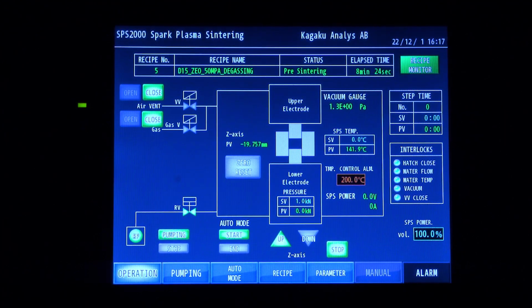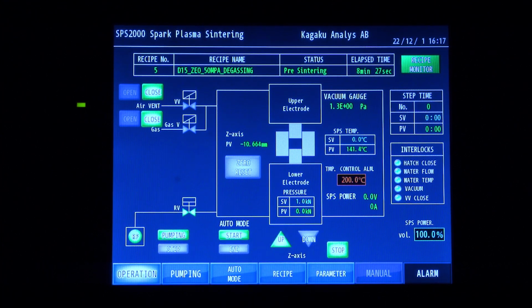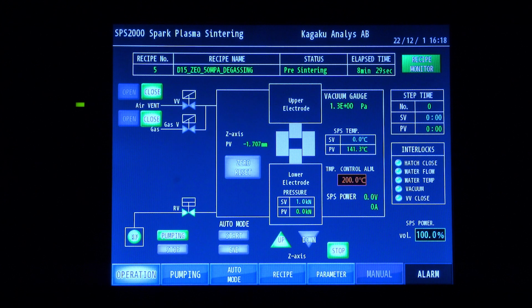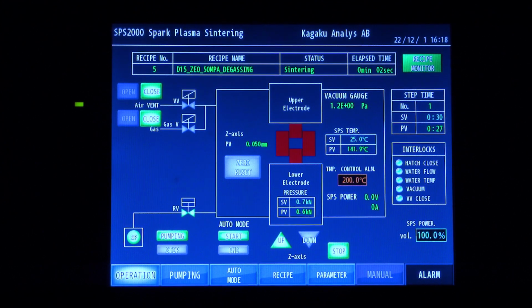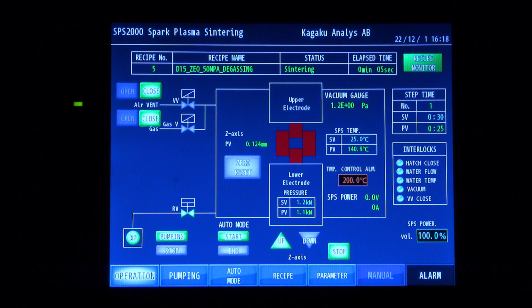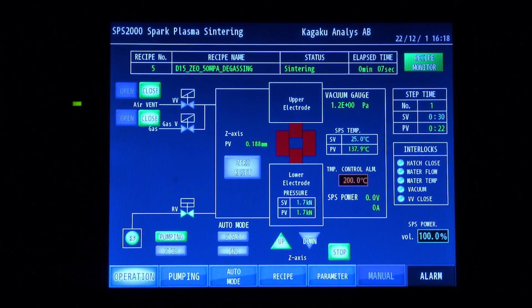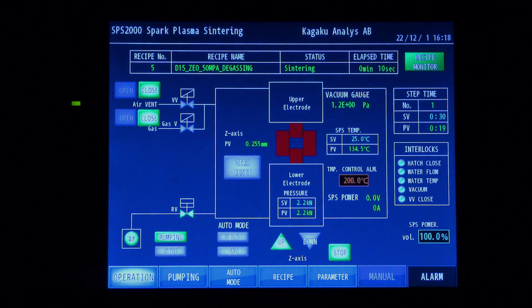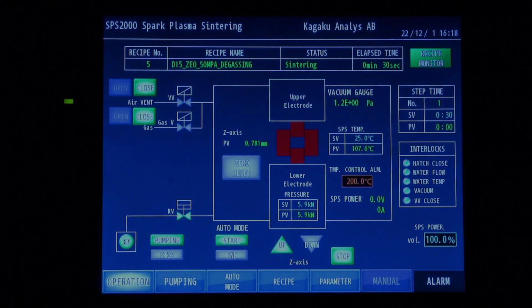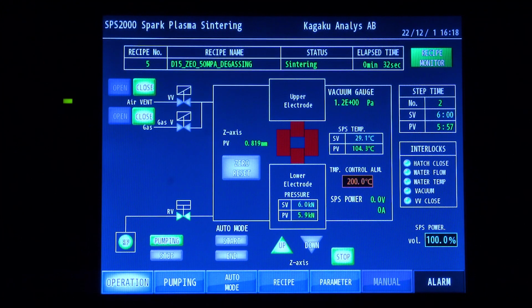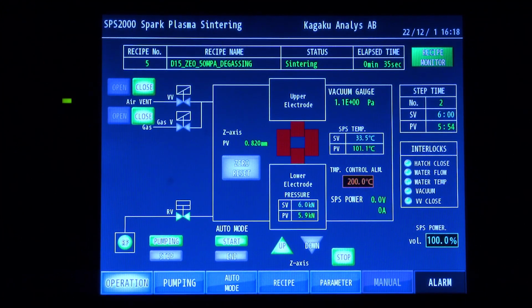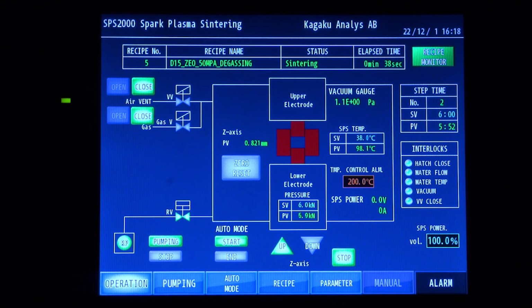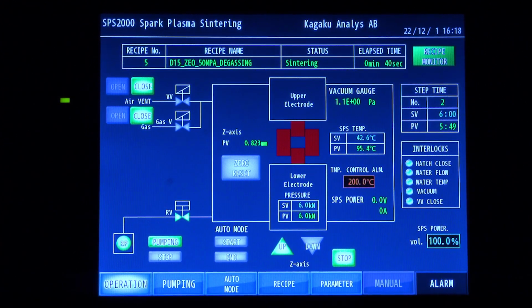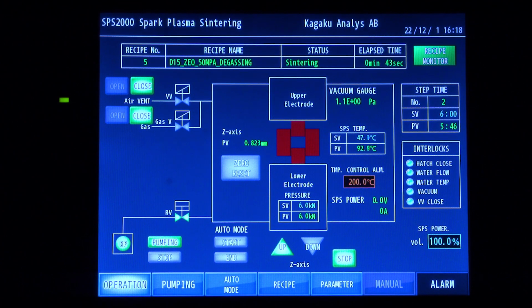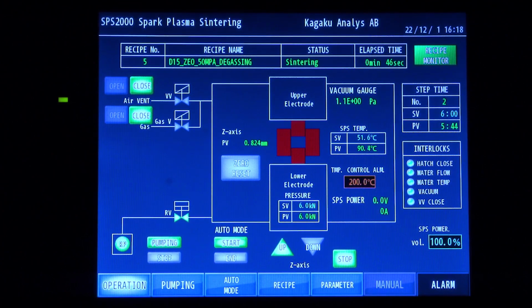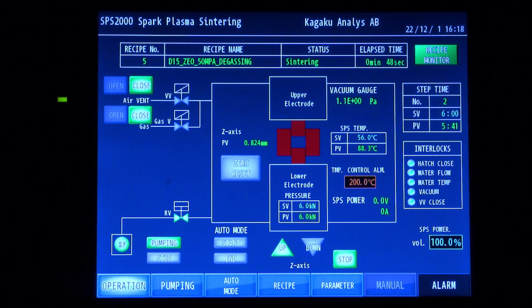So you can see that this set value of the pressure will change here when it reaches that position. And in the first minute here, it increases the pressure up to 6 kilonewton, which will give us 40 megapascal of pressure. Now we get into the second step of this program, and now the temperature starts counting from room temperature, but we are already, because of the degassing, at over 90 degrees. So it will take some time until we need some current to continue the heating.